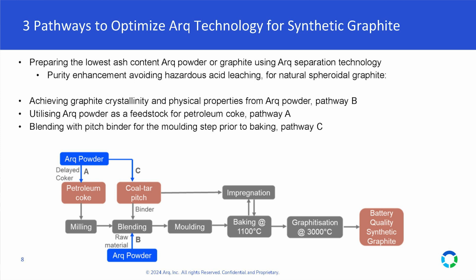So typically to produce synthetic graphite, you can take this as 4 stages: powder preparation, the molding and shaping side of things, baking, and the graphitization. So if you look, for example, at route A, we could potentially utilize our Arq powder in the pre-feed for the pet coke outcome. So in the actual delayed coker of the refineries, we can utilize our Arq powder with the pre-feed, which is the vacuum residue bottoms of the refineries, which we've done work on with the Western Research Institute.